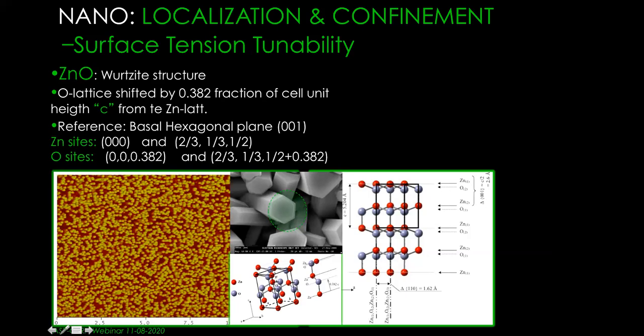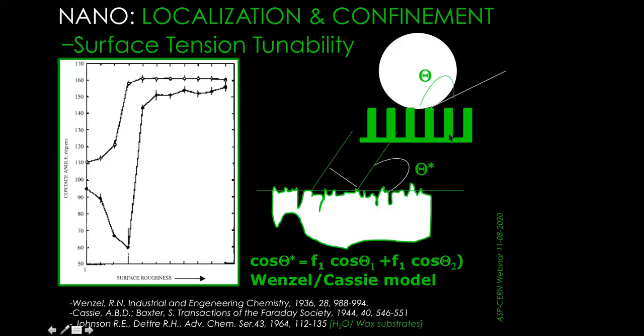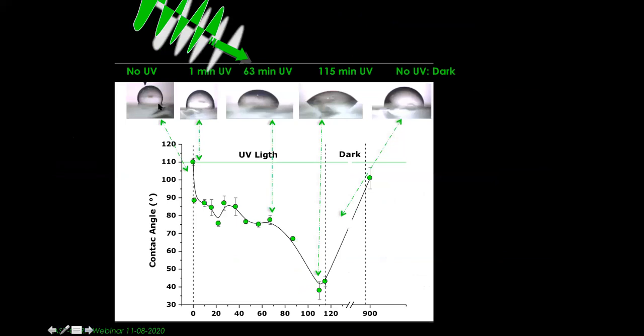So what happened is that if you take these nanorods of zinc oxide, they act like what we said. We have a very nice rough surface within which we control the height of these rods, and we control the distance between two successive rods. And if we do the experiments, colleagues, at the beginning, we put this droplet on that surface of zinc oxide that I showed you, this one. We put the droplets here, okay.